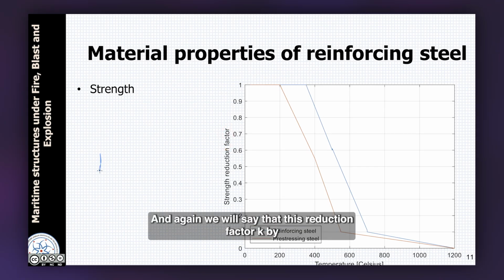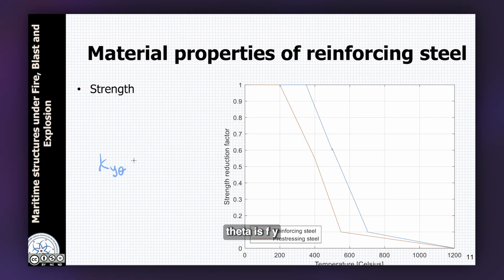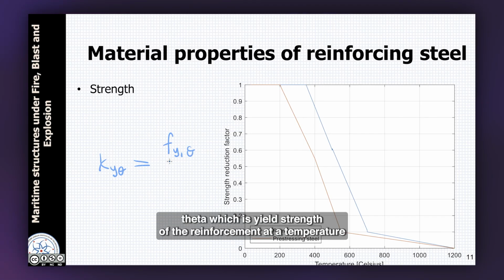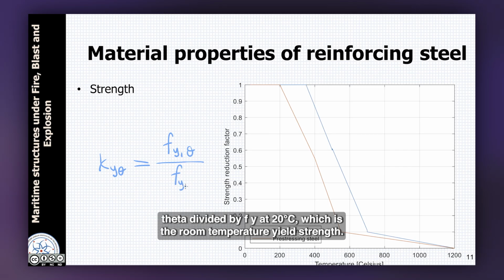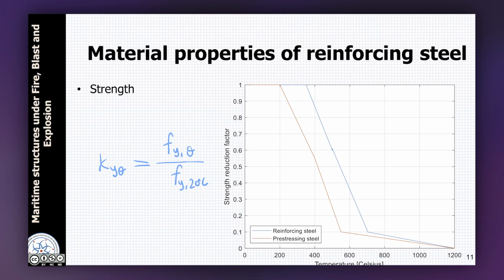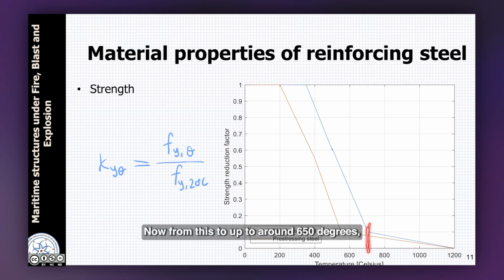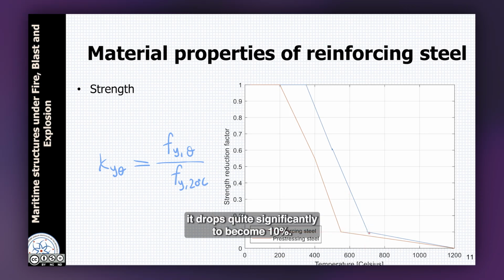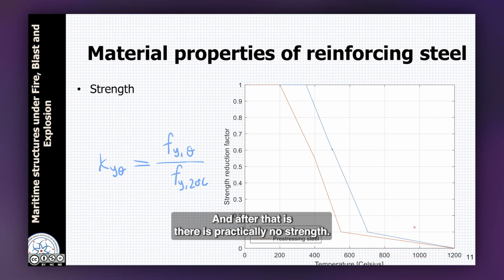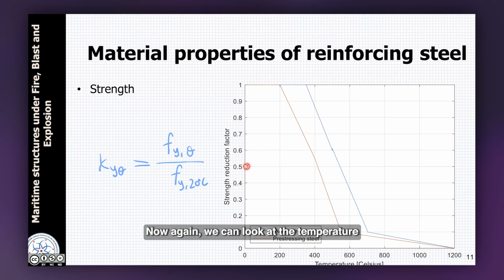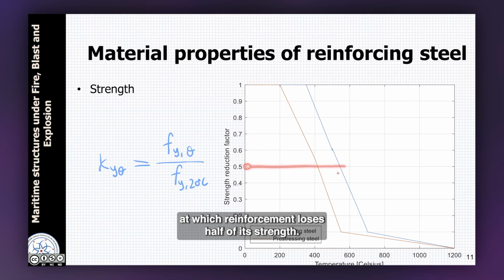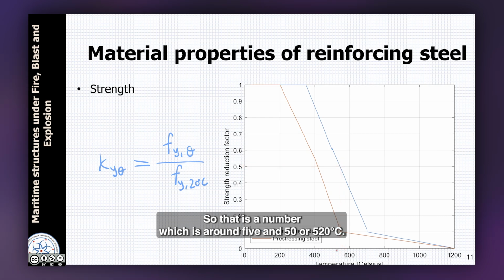And again, we will say that this reduction factor ky theta is Fy theta, which is the yield strength of the reinforcement at a temperature theta, divided by Fy at 20 degrees Celsius, which is the room temperature yield strength. Now from this up to around 650 degrees, it drops quite significantly to become 10%. And after that there is practically no strength. Now again, we can look at the temperature at which reinforcement loses half of its strength. That is a number which is around 550 or 520 degrees Celsius.